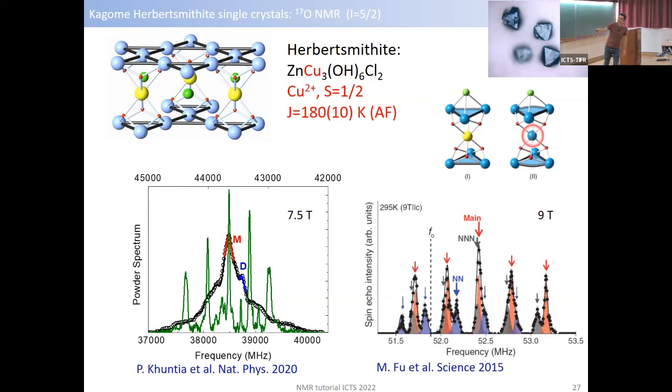We did that in Orsay, in my lab. It's been done at MIT. You get the same spectrum, basically. And so it tells you immediately that from the crystallography, you expect only one oxygen site. So you should have only 5 lines and that's it. So the fact that you see many more lines tells you that you have some different environment in your material.